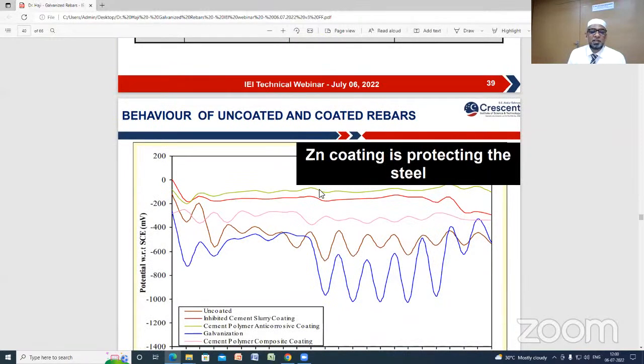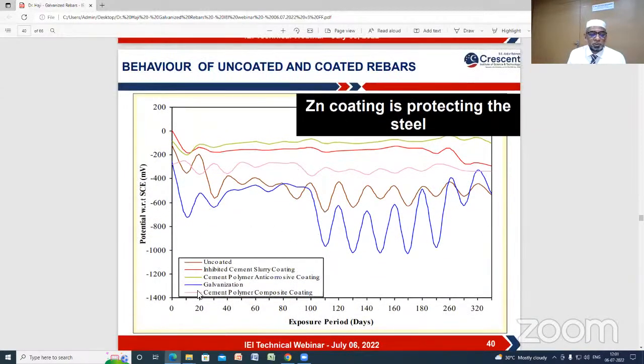So we monitored the behavior for 1 year. Here, the blue color curve shows the performance of the galvanized rebar over 1 year. We have to understand that the basic nascent potential of zinc is -1100. What happened in the 1 year duration is that the zinc starts consuming, but at the end of the 1 year there is still reserve zinc available. That means the steel corrosion had not started even after severe exposure to chloride conditions, pitting and drying. In the galvanized rebar, the zinc consumes and protects the steel rebar.